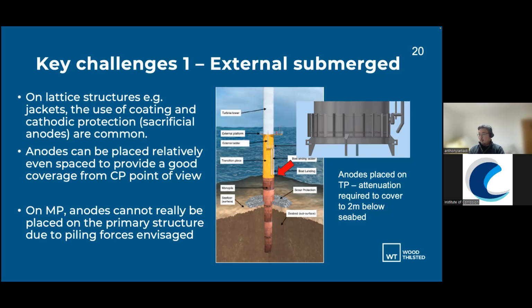The transition piece is where we put the majority of our anodes, but because it's only at one elevation, we need to consider how the interference factor would affect all the anodes together, because they are clumped quite closely, and also what is the attenuation that we're going to get from the anodes that are clumped together all the way down to the bottom. Now, the water depth that we're considering here is between 30 to 40 meters. So we need to consider, is the anode sitting at 0 meters? Can that actually give protection at 30 meters?